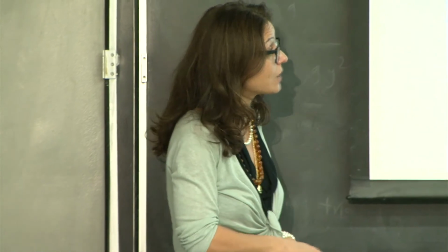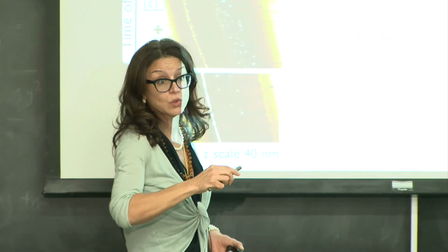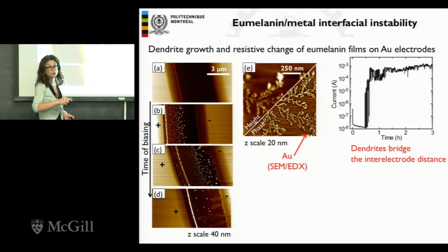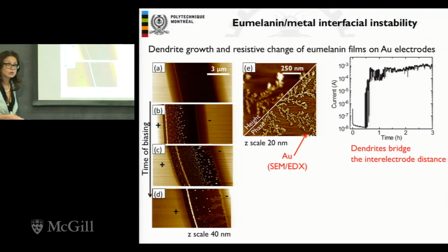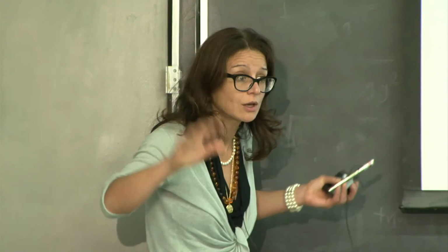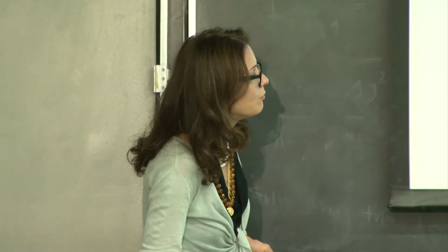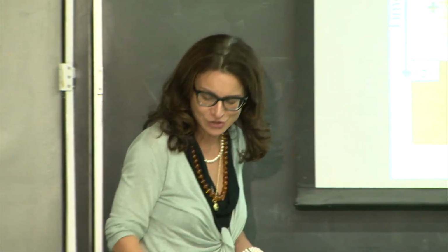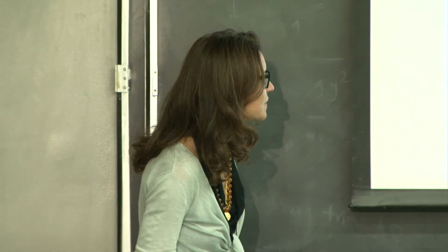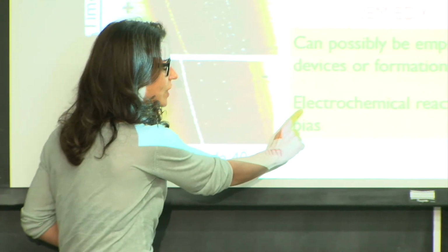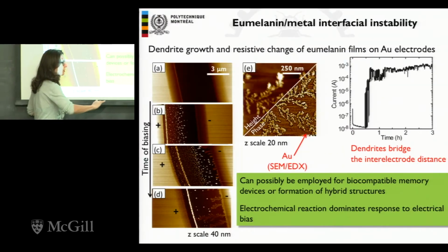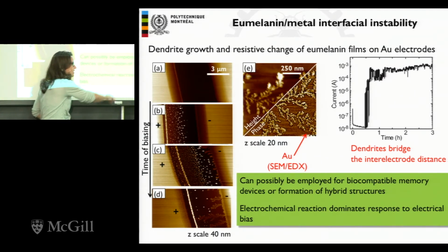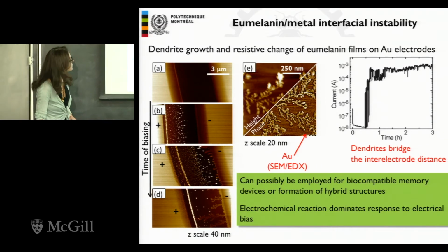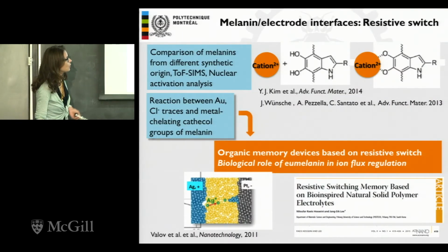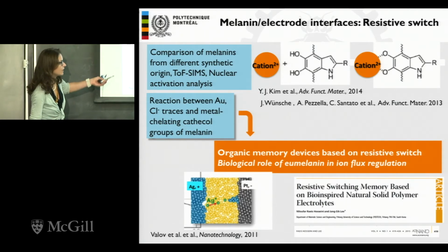Okay? So we observed actually a sudden jump of the current. We thought it was the conductive form of melanin. These are gold dendrites bridging the two electrodes. So if we don't want to be totally wrong, better to have an open mind. Otherwise, we can really make big mistakes. At the end of the day, this was a front cover in Advanced Functional Materials, so it was for good, but it was very surprising. So for instance, when you spin coat melanin extracted from natural sources on a patterned microfabricated substrate, and you are in a wet environment, electrochemical reactions dominate the response under electrical bias. This has been exploited. We are now working on resistive switching memory devices, taking advantage of this dissolution of the electrode, if the dissolution is controlled, of course.